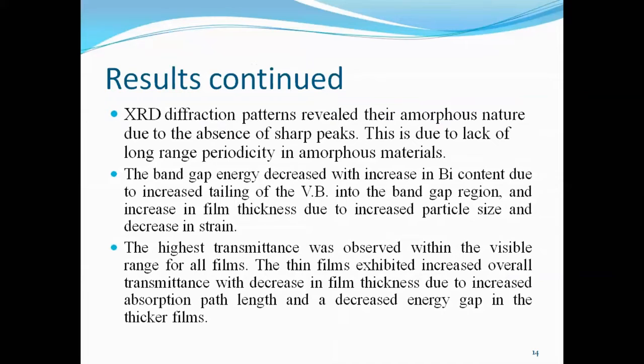Continuation of results. The XRD diffraction patterns for the 3 selected films revealed that they are amorphous in nature. Our thin films are amorphous, and this is due to lack of long-range periodicity in amorphous materials. I've not shown the diffractogram here for that.